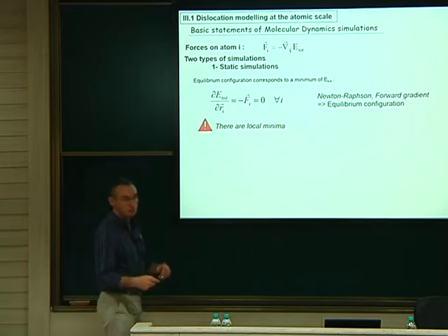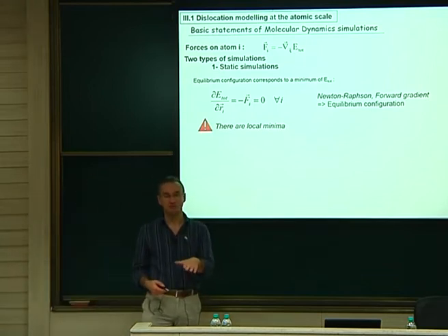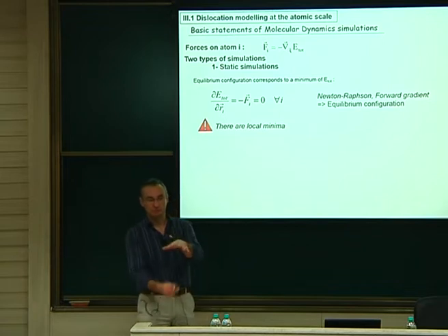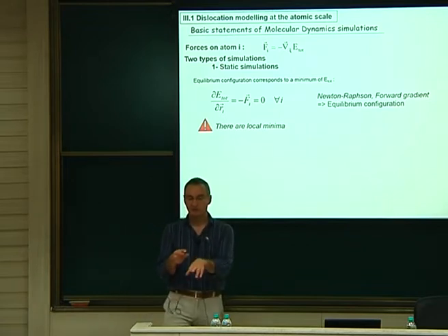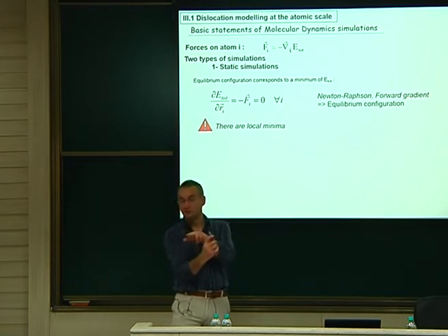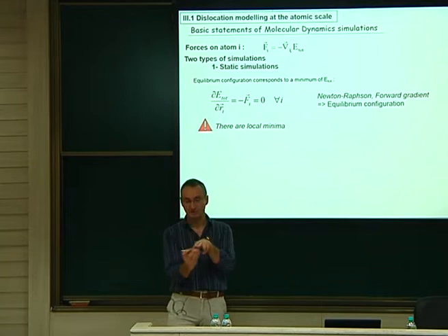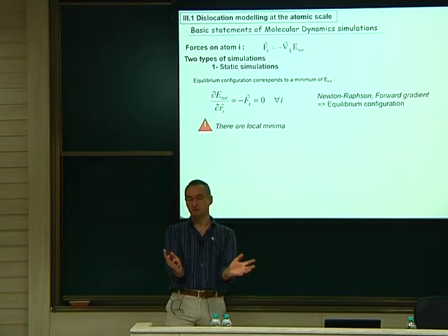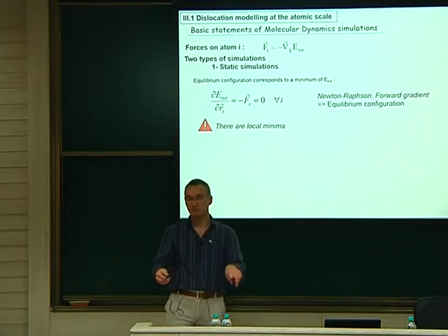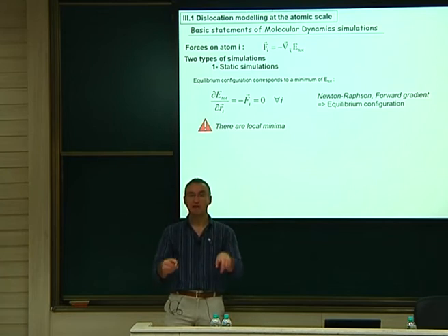This is typically what you should do if you introduce a dislocation in your simulation box. Usually we put the displacement field. So you take a perfect crystal, you remove an extra half plane, or you put your dislocation there. And then to put your dislocation, you add also some displacement field corresponding to your dislocation. So the Burgers vector, which translates one part of the space compared to the bottom one. You put this field, so it will distort your lattice. And then first you need to relax so that you will see the core splitting created. And this now is a physical start for your simulation.